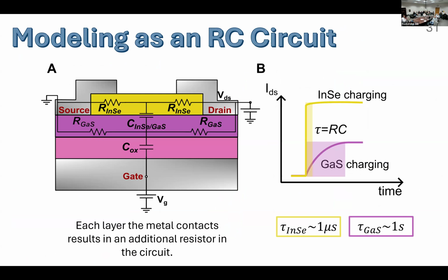So as Professor Berzofsky asked previously, how do I know that there's no current flowing through this device? Well, I did the measurements. I know that the resistivity of gallium sulfide is in the order of gigaohms, whereas that of the indium selenide is in the megaohms. So that change in the resistivity will induce another parallel plate capacitor that will increase the relaxation time. Relaxation time tau is related to the resistivity and the capacitance of the capacitor in the circuit. When we have the metal touching both of the pads, the R is no longer just the resistivity of the indium selenide, but also the resistivity of the gallium sulfide. So that will increase the charging and discharging time, hence the bi-exponential decay that we see in the order of a couple seconds in the time conductance measurements.